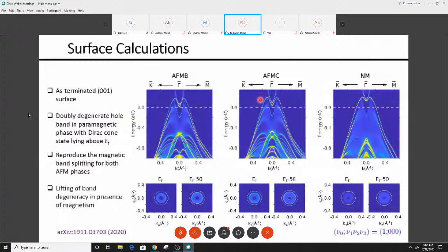which is consistent with the earlier argument that EuIn2As2 is a TCI in the AFM-B phase and a HOTI in the AFM-C phase. We can also see the band splitting is reproduced in both AFM-B and AFM-C phases.